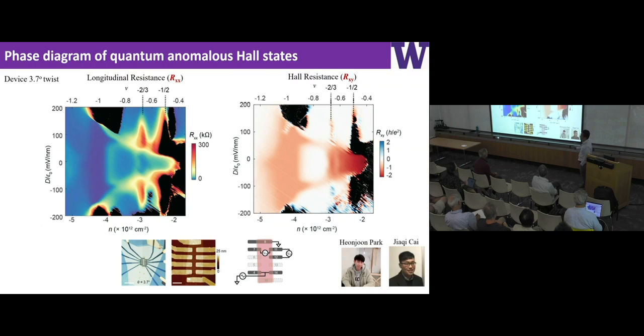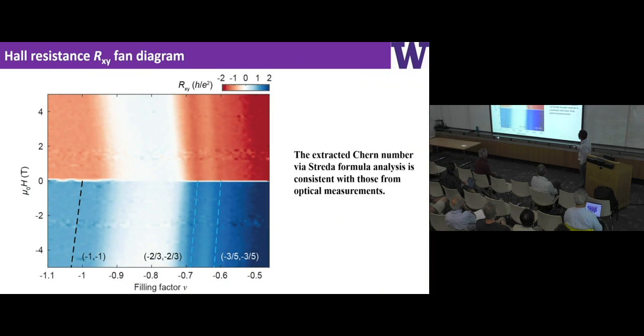There's a lot of things going on in these plots. You see, for example, at filling factors -1 and -2/3 a reduction, a compression, of Rxx, but at the same time an enhancement of Rxy. This already tells you there's something interesting going on, so let's do a little more careful study. I took these Rxy measurements and plotted them as a function of magnetic field. Basically, it's a Wannier diagram measurement, and you can clearly see three dispersing features. We can fit them to the Streda formula and get the Chern numbers -1, -2/3, -3/5.